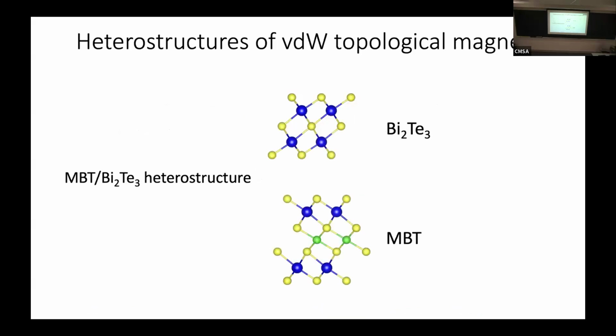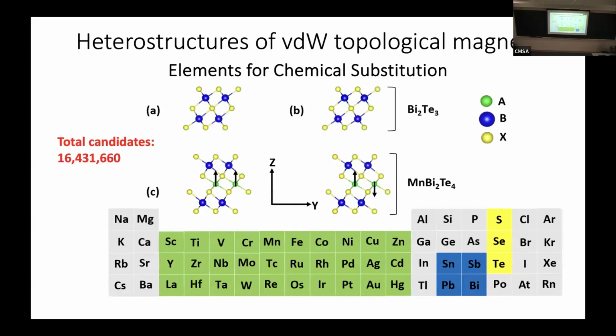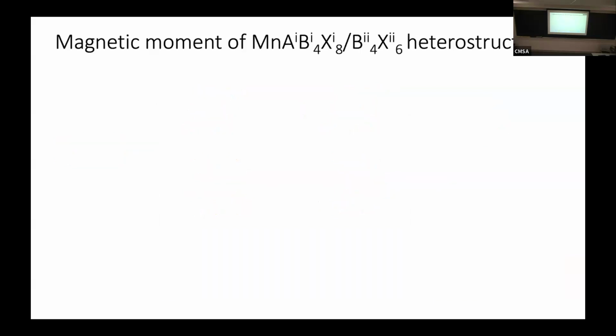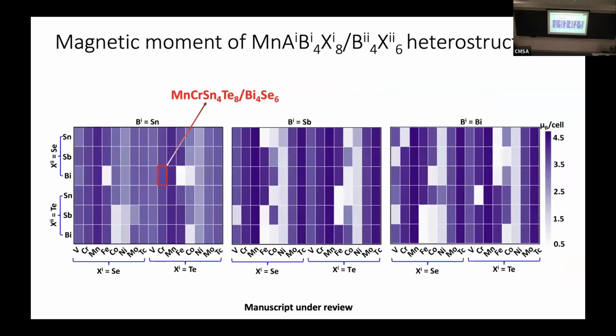So we put this MBT for one layer, bismuth telluride for the other layer, decorate the sites by substituting the manganese with different transition metals, bismuth with different elements, and the tellurium with different elements, sulfur, selenium, and tellurium. Then you get some data sets of DFT calculated properties. In this case, it was the magnetic moment. For instance, one heterostructure, manganese, chromium, tin telluride on top of bismuth selenide is here.